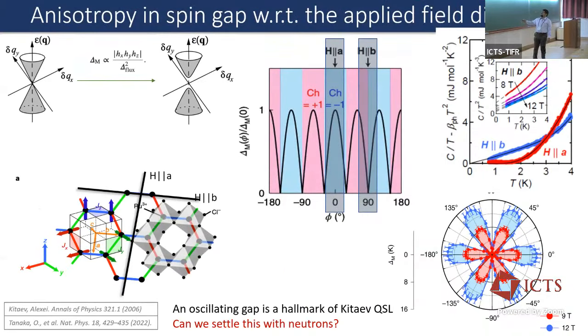So what they found is that when you apply a field H parallel to A, where your Chern number should be finite, you see gap behavior, like an excited behavior. And where you have H parallel to B, it slowly extrapolates to zero, almost gapless.